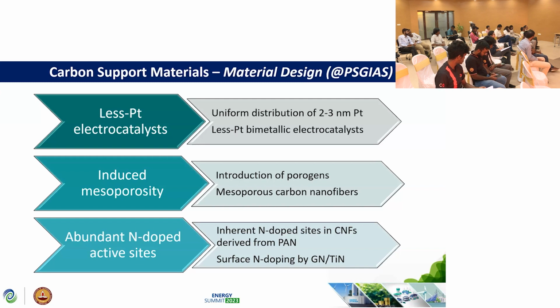We try to introduce some porogens, and then we produce mesoporous carbon nanofibers. Of course, with our methodology, we create abundant nitrogen active sites. These originate from the inherent nitrogen sites in the carbon nanofibers, since we are using polyacrylonitrile. We are also trying to introduce abundant nitrogen active sites by deposition of a surface layer of graphitic carbon nitride or titanium nitride on the surface of the carbon nanofibers.